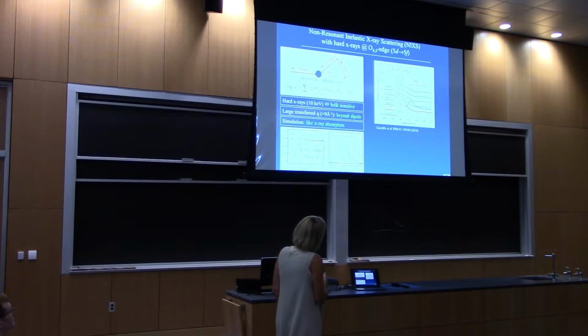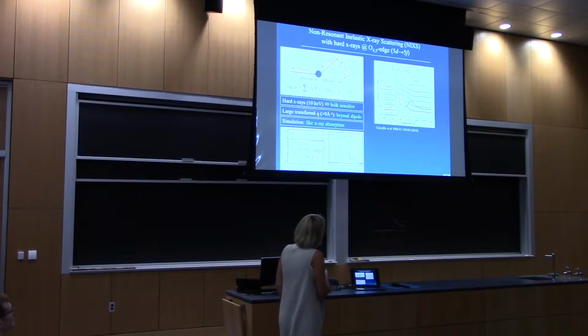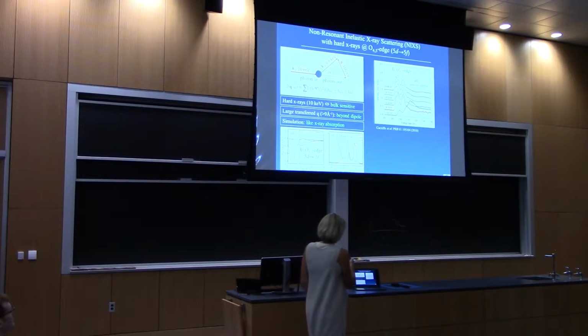You see this dipole shape here, it is rather funnel-like. This is not in these calculations because we use the same line width for all the multiplet excitations in our calculation. Whereas when you go to large momentum transfers, like here, you really have these very sharp excitations coming up, and these are the non-dipole excitations, we call it.